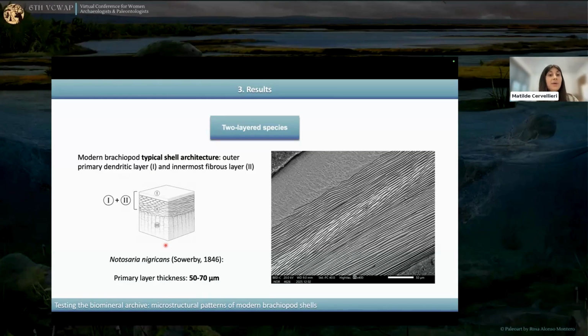They display the typical shell architecture with an outer primary layer and an innermost fibrous secondary layer. And in the SEM image, we can appreciate the species Notosaria nigricans from New Zealand. And this is quite interesting as the primary layer thickness is between 50 to 70 microns, whereas it has been reported in literature that the primary layer thickness ranges between 20 to 40 microns.